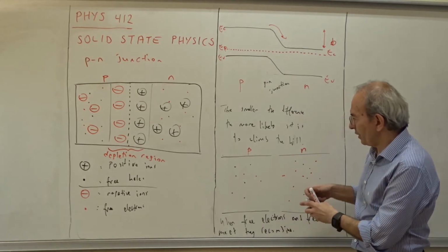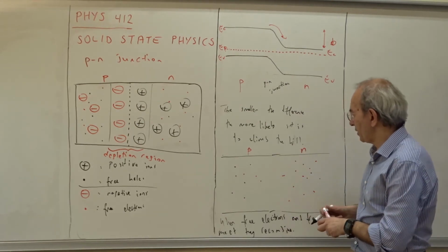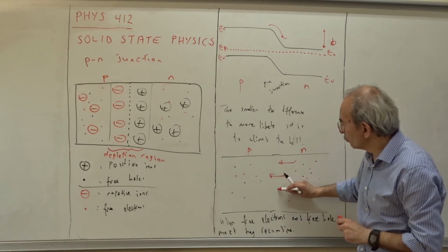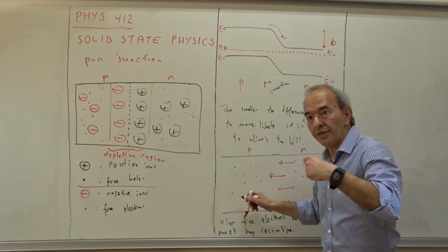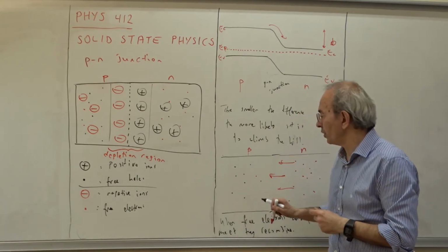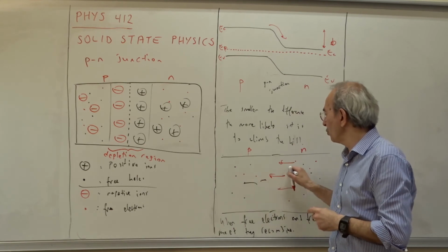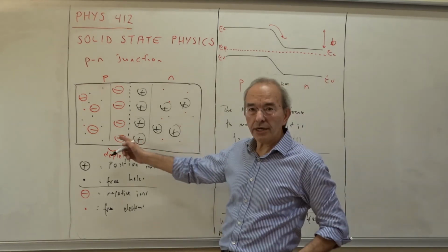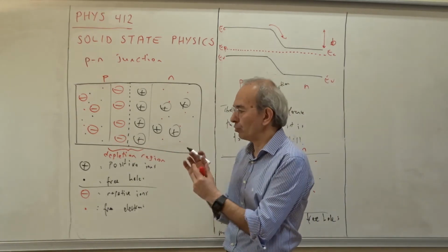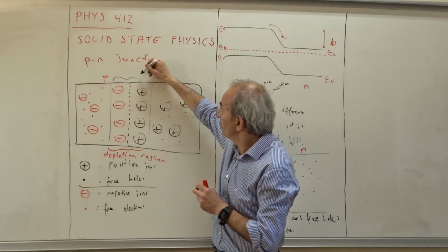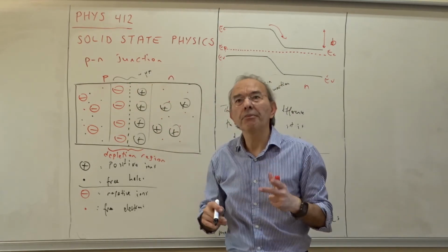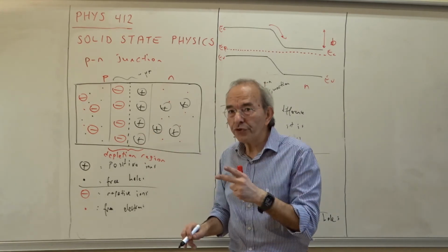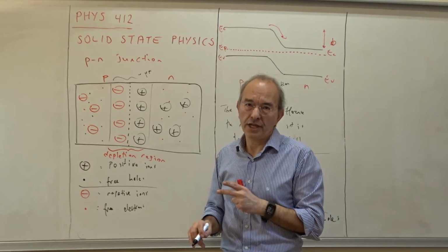Let me join them. Consider this as that single p-n junction. So these particles move to the other side because there's a very large concentration of free holes, and these free holes and those electrons just recombine, so that in this part, up to some certain limit, on the order of, let's say, a micrometer, a very short length, there is no free electron and no free hole.